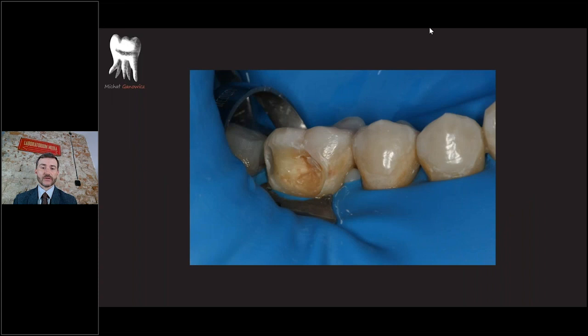And so you will see some of my cases, cases when you can use the Biodentine. For example, this patient came to my office. There was a really huge composite filling here, and there was a big leakage in this filling. So there was secondary caries here, and this caries was very close to the pulp. It was a really perfect indication, a perfect case for the Biodentine, because the patient has no signs of pulpitis, and there was no problem of the occlusion with the Biodentine, because all the occlusal forces are working here, not here. So in this perfect situation, we can leave this Biodentine for 6 months without any problem.